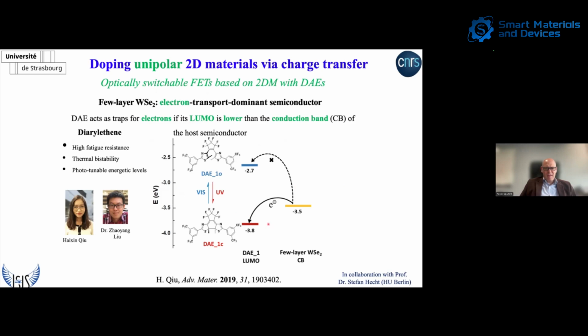And together with Stefan Hecht in Berlin, our synthetic partner, we designed it such that its LUMO level was falling outside the band gap for the open state and inside the band gap of the tungsten diselenide for the closed state. So now, let me explain what it means to have a dopant whose level falls in the band gap of a semiconductor. This means that the dopant will act as a trap for the charges of the semiconductor, whereas when the dopant level falls outside the band gap of the semiconductor, the interactions are purely electrostatic. So essentially, we can dope and undope, or trap and untrap, our 2D semiconductor.